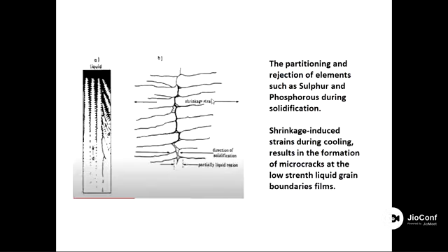To understand the solidification cracking issue, these low melting elements like sulfur, silicon, and phosphorus tend to segregate at the grain boundary. During cooling, when the weld cools, shrinkage takes place. The shrinkage pulls apart the two grains at the grain boundary, and literally a crack is observed. So these are micro cracks.